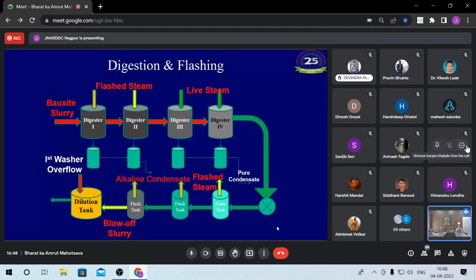In the dilution tank, we add the first washer overflow to dilute it. The reason being, the alumina liquor, sodium aluminate liquor, is supersaturated and it is present along with the mud. So there are all chances that it will auto precipitate. To prevent auto precipitation, we reduce the concentration by diluting the system, and that also reduces the viscosity so that you can settle out the liquor well.